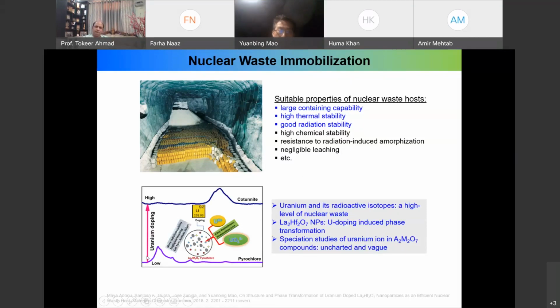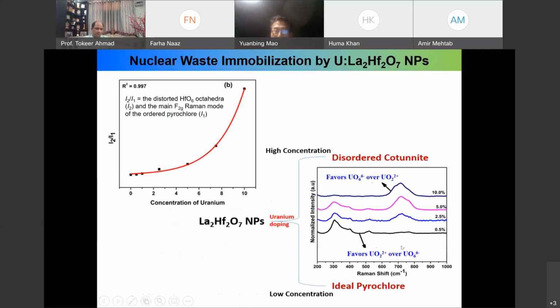This is from our study showing that we can dope different amounts of uranium into this type of lanthanum hafnate nanoparticles. For example, here we showed from low to high, up to 10%. And the materials are pretty good. Here I'm trying to show you the Raman spectrum, and you can see that different uranium ions are actually preferred at different doping levels. When the doping level gets higher, uranium ions have different forms. This is related to what is called speciation.